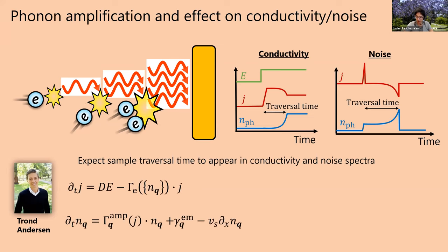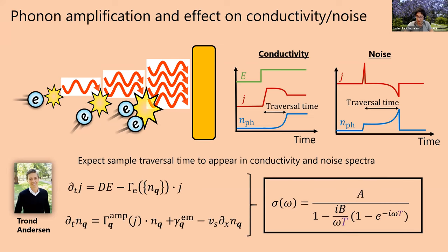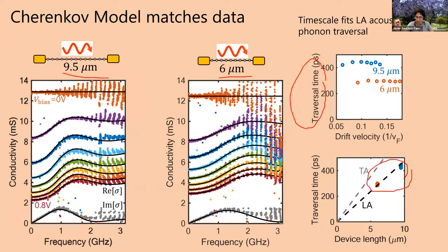I'm not gonna go into this model anymore, just say that Tron developed it, it was very nice. Described very well in our paper. An important point though is that this model fits very well our conductivity data, okay? And actually fits it with only one fitting parameter, which is the time it takes for a phonon to transit from one side of our device to the other.